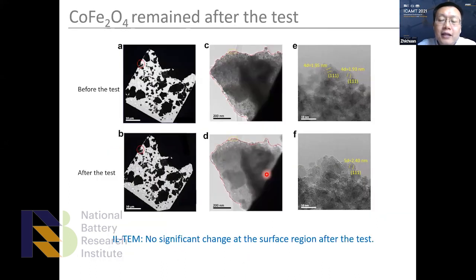And then we suspect there might be a change on the electrode surface, for example, the cobalt iron oxide surface gets reconstructed, and then we observe the increment. So this could be a possibility. And then we use identical location TEM to observe the surface, exactly the same region before and after the test. And we found there is actually no significant surface reconstruction. So the increment cannot be ascribed to surface reconstruction.